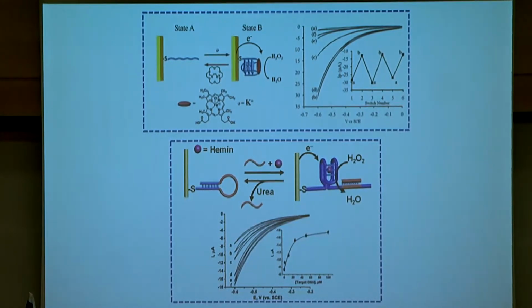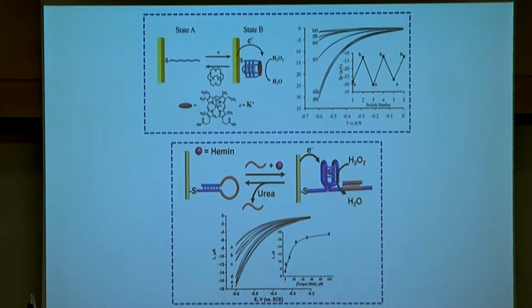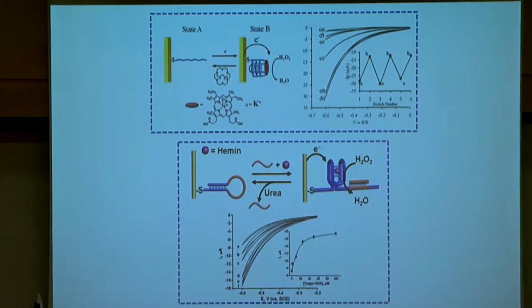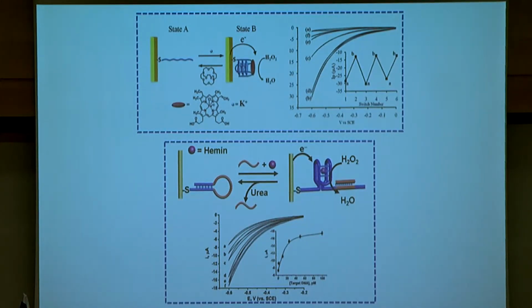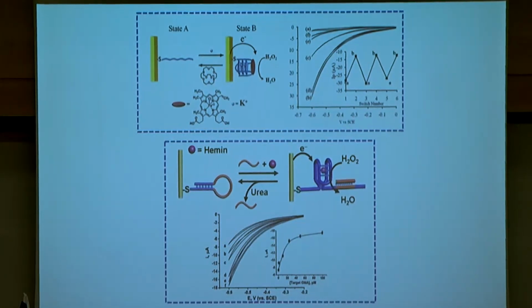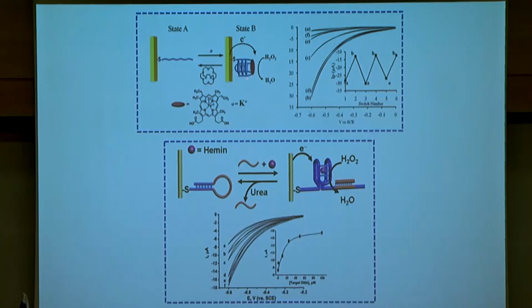So what we were able to show is that we can take a single-stranded thiolated nucleic acid rich in guanosine bases in the presence of potassium ions. On the surface, it self-assembles into a G quadruplex, and this G quadruplex binds various transition metal complexes like hemin, and once we bind the hemin, we get an electrocatalyst for the reduction of hydrogen peroxide to water. When we add crown ether to this system, we are able to separate, by taking out the potassium ions, the G quadruplexes and we get a random coil. So we can switch on and off the bioelectrocatalytic activities of these elements.